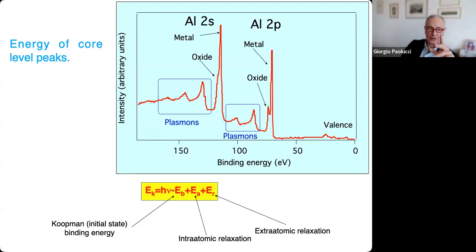There are a few tricks involved in this statement, but normally the peak related to the oxide is at higher energy than in the metal. And then, of course, if it is not oxygen, if it is another atom, you can actually look at the changes. You look at the tables and model samples, and you can get information on what kind of oxidation state you're looking at. And this is easier in this spectroscopy, with the limitations we have, compared to absorption, for example, because this spectroscopy requires vacuum and you're looking at the surface. So if you want to look at the bulk and you think that the surface is different, that's not a good idea. On the other hand, you're basically separating the initial and final state effects. I mean, you don't have final state effects, so you can think in very simple terms.